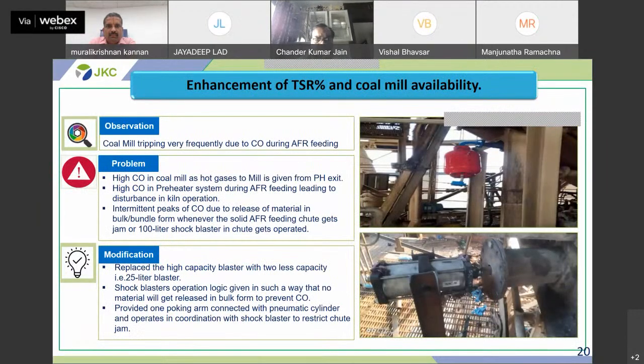The next project is enhancement of TSR percentage and coal mill availability. Coal mill was tripping very frequently due to CO problems. High CO in preheater system during AFR feeding led to disturbance in kiln operation as well as coal mill operation. Intermittent CO peaks occurred due to release of bulk material whenever the 100-liter blaster gets operated.